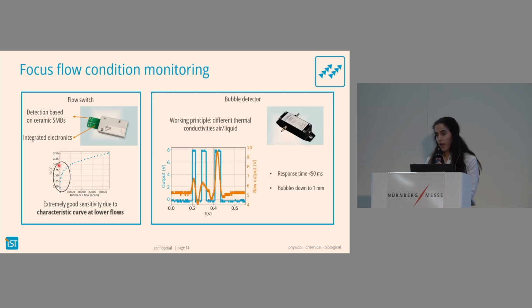And we also have a solution that is for liquids. So it's measuring bubbles or gas inside the liquid. The working principle here is because we have different thermal conductivities between these two elements. And what you see here is in orange what the heater behavior would be when several bubbles are coming in, bubbles that are below 1 millimeter. And the blue signal is the signal that the bubble detector gives. So it's like an on and off signal.